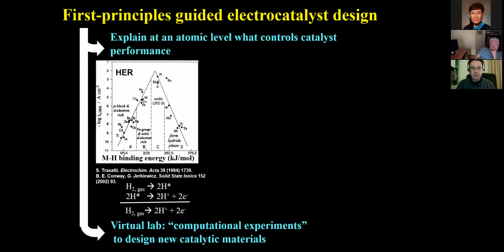So to give you a picture, an example of what that looks like from a DFT standpoint, we can use these first principles, quantum chemistry, density functional theory methods to study heterogeneous solid catalyst surfaces for generally two purposes. One, to explain an experiment that was already run. So try to understand why, in this case, the hydrogen evolution reaction, or I wrote here in the opposite direction, the hydrogen oxidation reaction, why platinum seems to be the best catalyst for that reaction most typically.